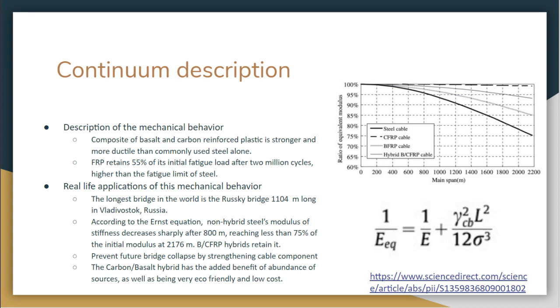The composite of basalt and carbon reinforced plastic has higher yield strength and better ductility than the most commonly used steel. Unlike steel with its low fatigue limit, FRP retains 55% of its initial fatigue load after 2 million cycles. An example where bridge length of this caliber becomes relevant is when we start talking about the longest bridge in the world, the Russky Bridge in Vladivostok, Russia, at a whopping 1,104 meters.